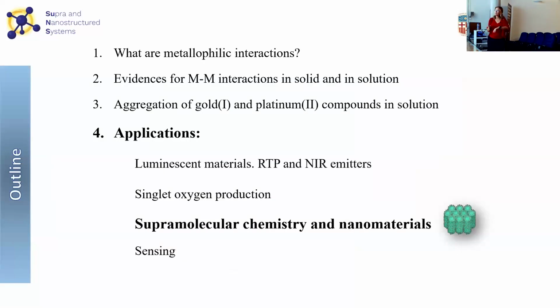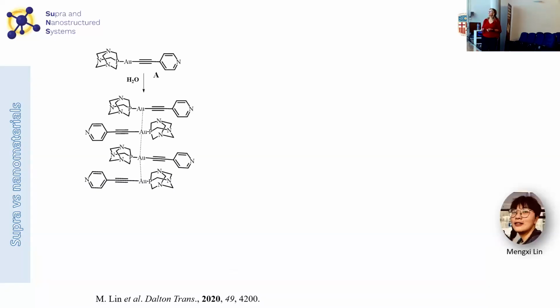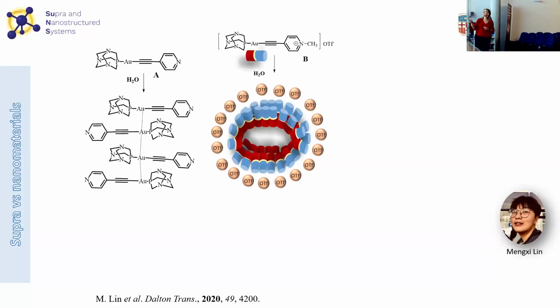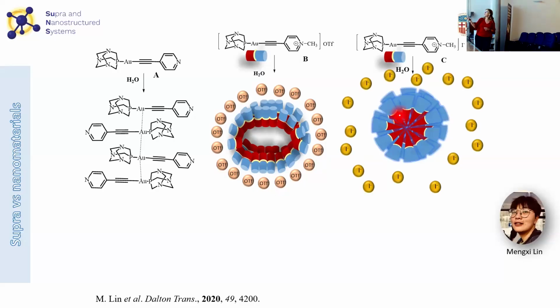So let's move very fast to the last applications. One is the interface between supramolecular chemistry and nanomaterials. So I thought that being here at the ICMAB, I should talk a little bit about something on materials. So for this, I decided to put one of the examples. First of all, remember that I explained that this molecule can give rise to the formation of some hydrogelators. When we introduce a positive charge in the molecule, we can have some kind of square-like structure and some kind of spherical vesicles when we change the counterion from a triflate to iodine.